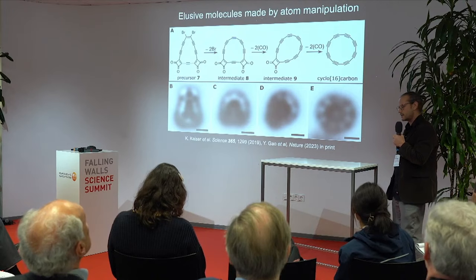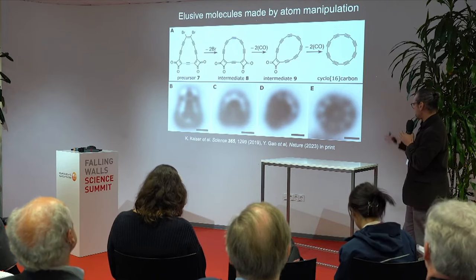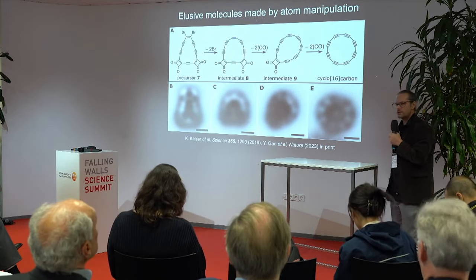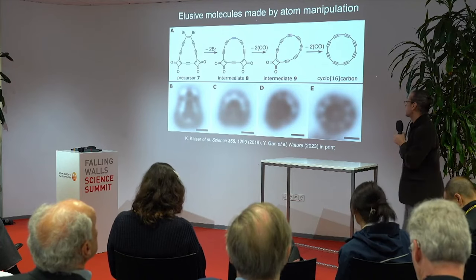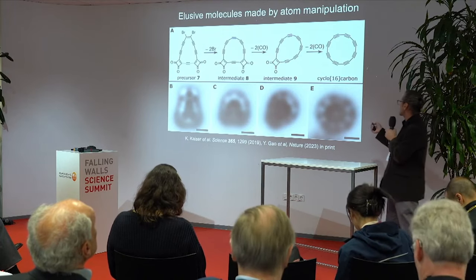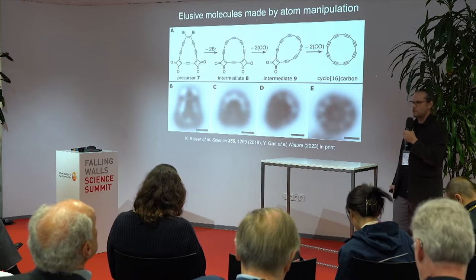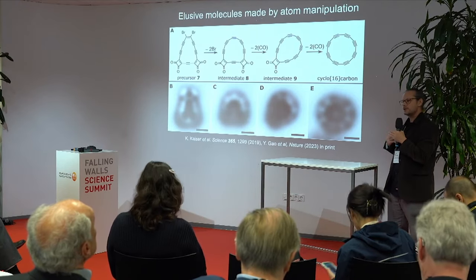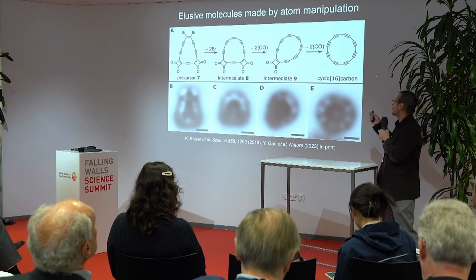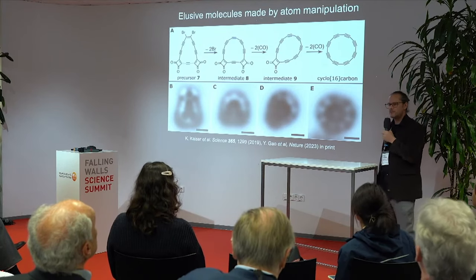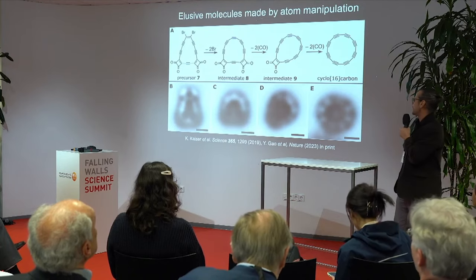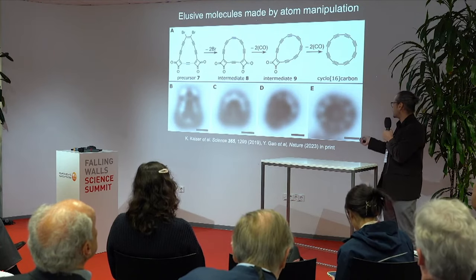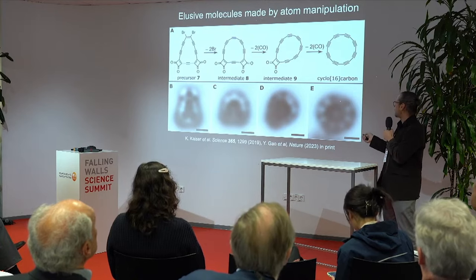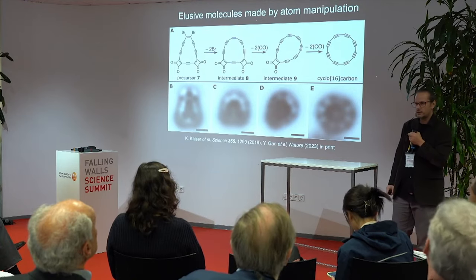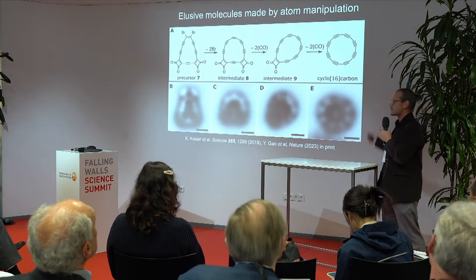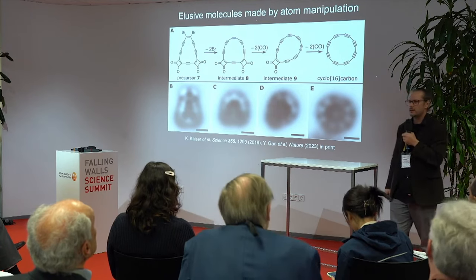And here our technique does not only show you basically the atoms, but you also get information on the strengths and the lengths of bonds. And in these cyclocarbons, there's often the question whether these are cumulenic structures or polyynic structures, meaning whether they have just double bonds all around or they have alternating short and long bonds, triple and single bonds. And with our AFM, we see these short triple bonds as bright protrusions. So we can actually, from this image, tell that this molecule is in the structure with alternating long and short bonds.